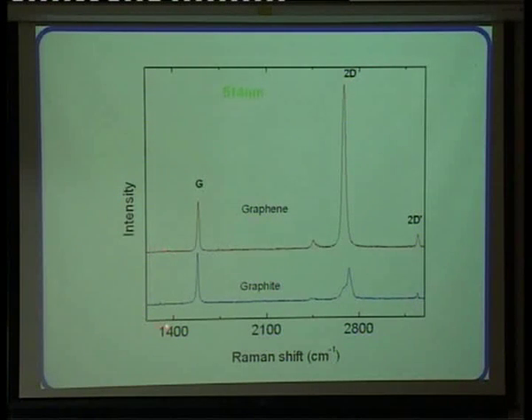The D peak is not seen at all in the Raman spectrum because it's forbidden. It doesn't satisfy the selection rule. But the sum of the Q plus minus Q is 0, so you see the 2D peak. So there's no big science there. It's actually very simple science. What is a bit strange, and it took quite a few years to understand, is why the intensity of the peak is so large. On the other hand, if it's so large, it's good because it's easy to see and characterize the samples.